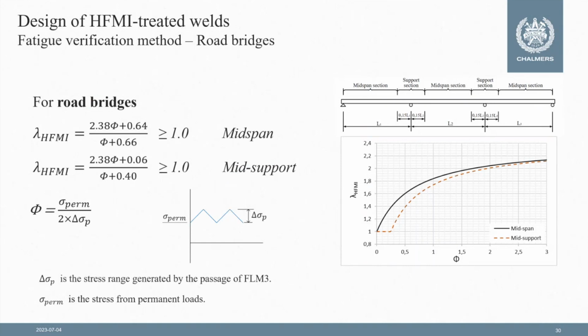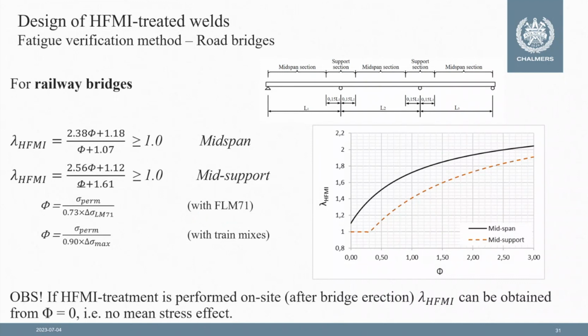So in a very similar way to lambda 1 in the current rules for fatigue design, we distinguish between the support section and the mid-span section. We have two curves that describe lambda HFMI, dependent on phi, which is a factor that describes the stress range, delta sigma p, and the mean or the minimum stress that is coming from all permanent loads. So phi is sigma permanent divided by twice delta sigma p. That describes the R ratio effect coming from the load model, and then it's correlated to a lambda HFMI, which is then used on the load effect side. So for road bridges this was derived, and similar curves are derived for railway bridges.